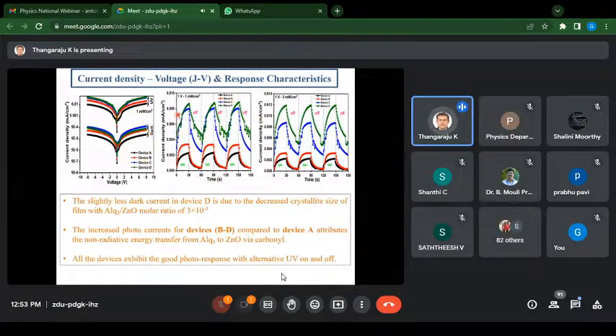And the response also, you can see that upon increasing the AlQ3 content, the response is drastically increasing when compared to the pristine zinc oxide based devices.